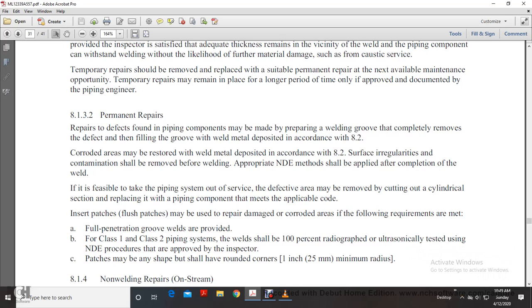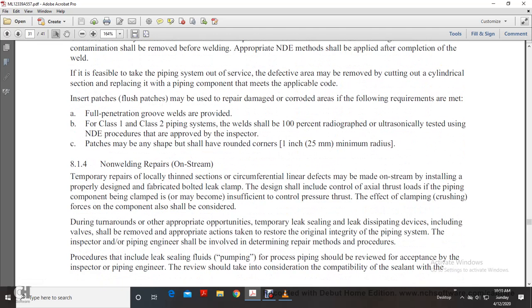If feasible, taking the piping system out of service, the defective area may be removed by cutting out a cylindrical section and replacing it with a piping component that meets the applicable code. Insert patches, or flush patches, may be used to repair damaged or corroded areas if the following requirements are met: full penetration groove welds are provided for Class 1 and Class 2 piping systems. The welds should be 100% radiographed, or ultrasonic testing used, in accordance with examination procedures approved by the inspector. Patches may be any shape but should have rounded corners with a 1 inch minimum radius.